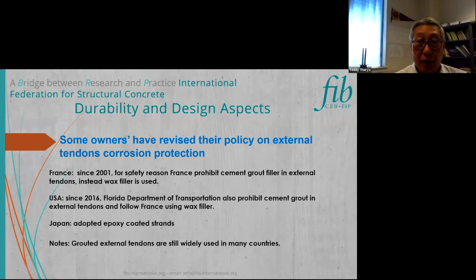Some owners have revised the policy on external tendon corrosion protection. For example, France and Florida Department of Transportation in the US have implemented using wax filler instead of cement grout. So both of these owners prohibited cement grout filler in the external tendon bridges. In Japan, using a different approach, Japan adopted epoxy coated strand. But keep in mind also, grouted external tendons are still widely used in many countries. If this is done properly, grout also can provide a good protection to your tendon.